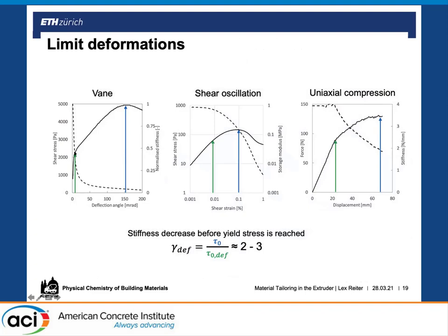If we look at, for example, here at the plot, you can observe the linear part at the beginning, and from that point on, you have on the x-axis a deformation that is viscoelastic or creep or whatever, and that deformation is something that would also result in the print. So that would be associated with this sagging, but I haven't done any calculation from the characterization tests over to the print. The way that we are dealing with it is that we just increase the accelerator dosage until it works, in a stupid and simple way.